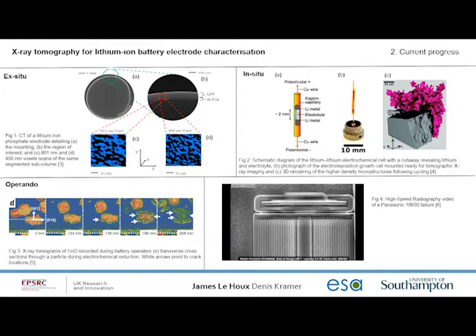So what we can see here in this picture on the right, this copper wire has a window made into it, which can then be used as the imaging center. We then assemble our lithium metal, and we're looking with electrolyte, and what we're looking at is the deposition of this lithium metal on the substrate. So there's a compromise in this case between the image quality and the accurate battery performance, because we're getting further away from the battery. But as you can see on the far right with that beautiful pink picture, we can see these lithium dendrites being formed on the substrate.